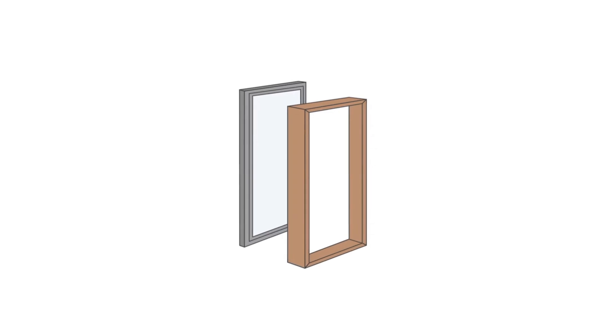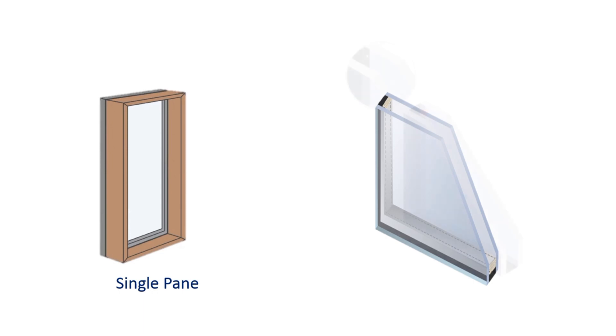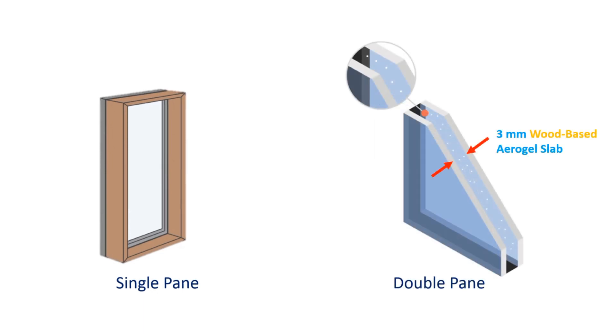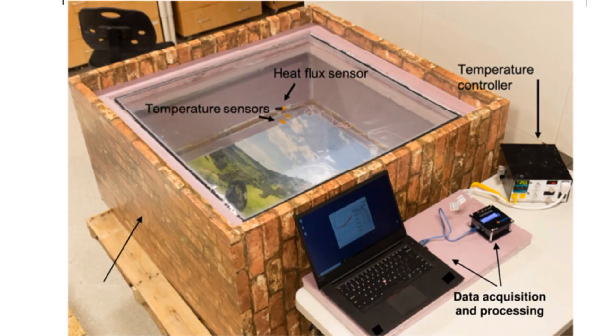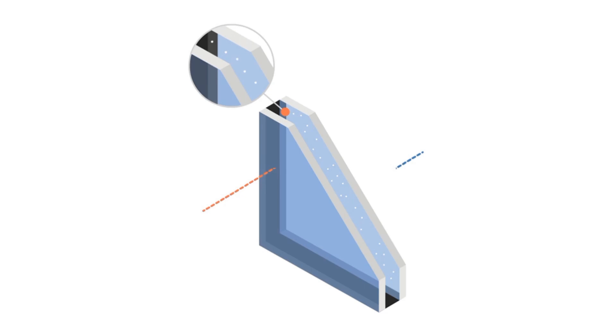To test the materials, the researchers placed the wood aerogel film on the inside of a single-pane window glass and put a 3mm thick slab in the gap between two panes of a modern window. They placed these test panels in the openings of hot and cold boxes with inside temperatures of 40°C and minus 20°C, mimicking summer and winter temperatures. What they found was quite promising: the wood aerogel-containing windows more efficiently blocked heat flow between the inside and outside of the boxes.